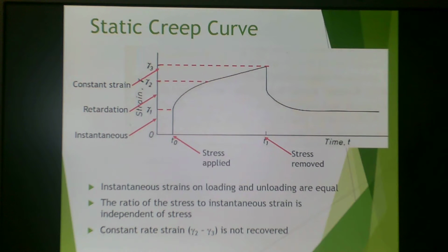Instantaneous strains on loading and unloading are equal. The ratio of the stress to the instantaneous strain is independent of stress, and the constant rate strain from gamma 2 to gamma 3 is not recovered.